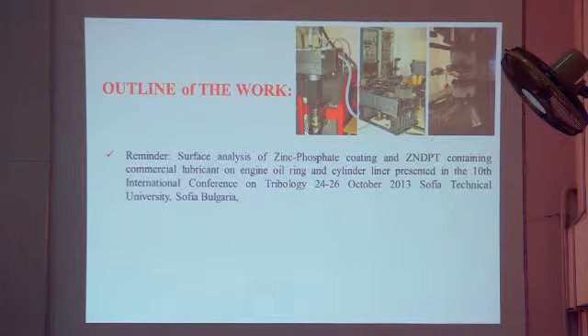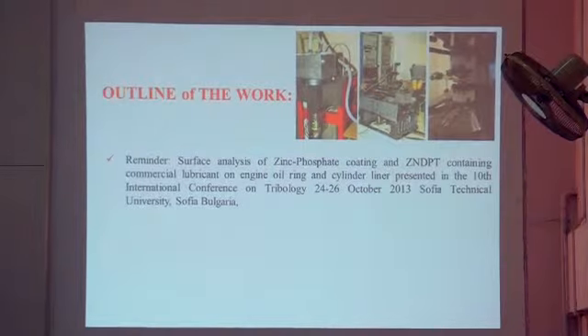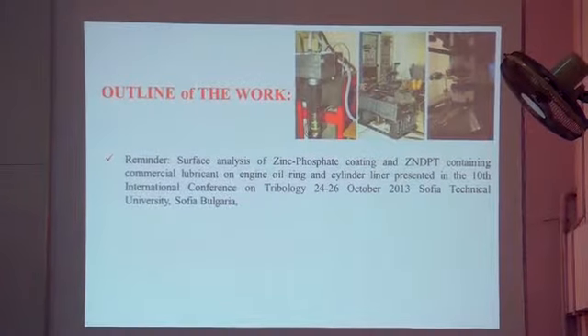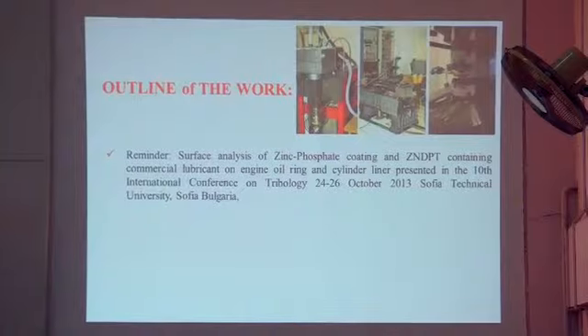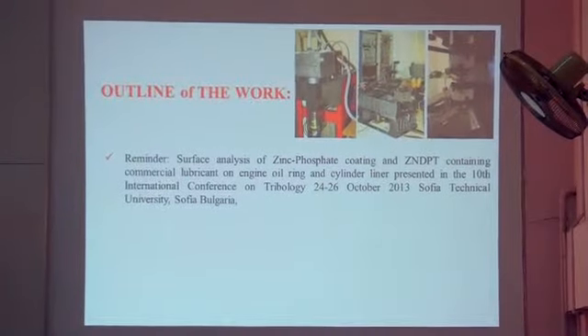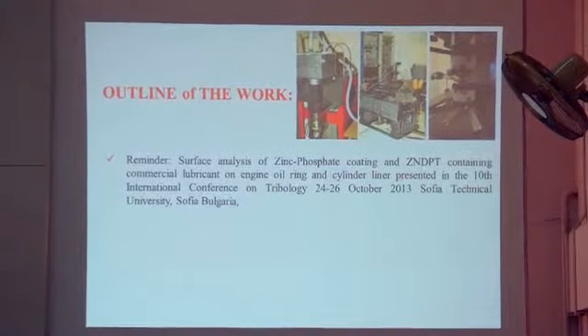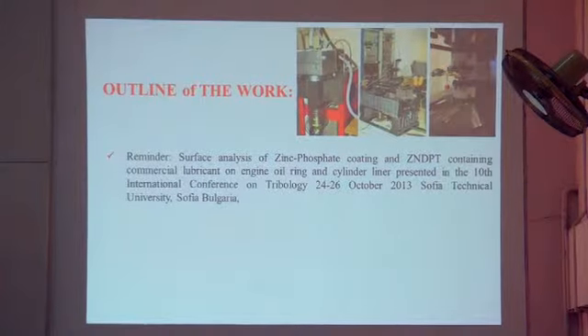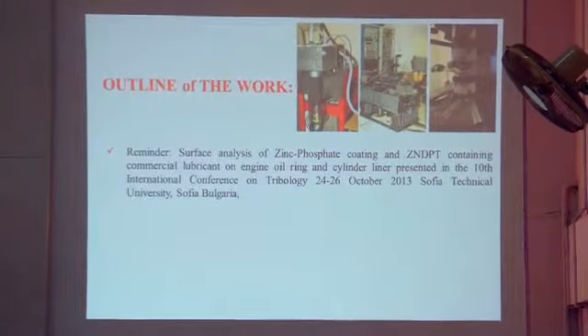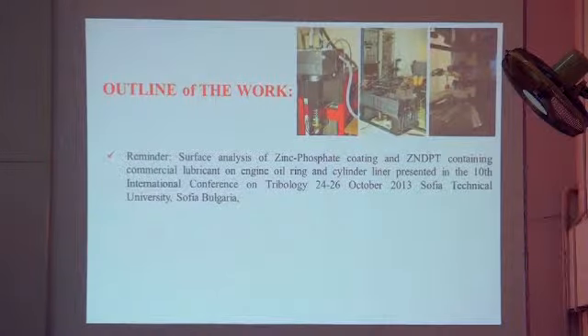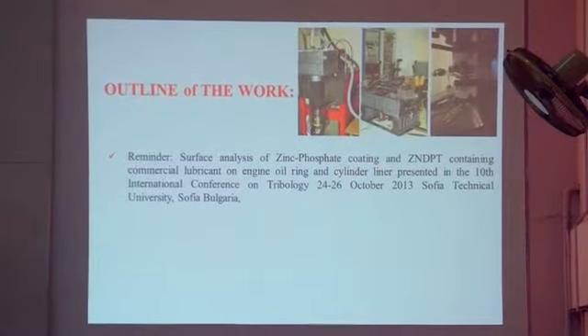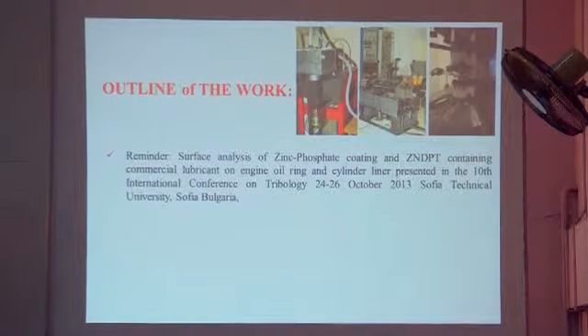When we were doing some engine tests, we detected very interesting results, which I presented yesterday. We tested different piston rings on the cylinder liner on a test rig, and it was very interesting because oil contains some additives, mostly ZDDP, calcium sulfonate, etc., like anti-wear agents, antioxidants, etc.